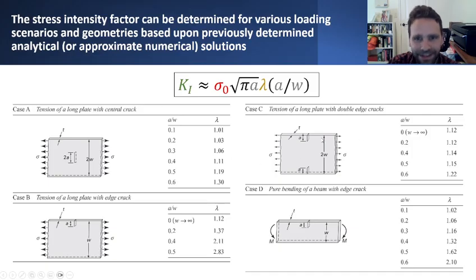So this kind of gives you a sense, and I've taken some of these tables directly from the textbook, showing how you might compute the stress intensity factor using this sort of approximated expression that involves that original classical result for the case of an infinite plate with a crack of width 2a, but also multiplied by some additional, we'll call it a geometry factor. It's a geometry dependent correction factor that depends on the crack size a, and possibly normalized by things like the dimension or width of the plate in the case of a plate-like geometry to which we're intending to extend the original expression for the stress intensity factor.